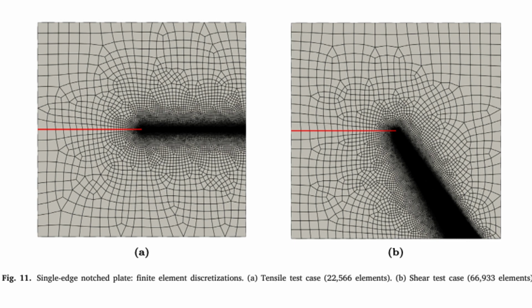This is where their novel line search comes in. Instead of monitoring the energy value, they decided to monitor the energy gradient, specifically the derivative of the energy functional with respect to the step size, lambda. Okay, explain that. They're looking at the slope instead of the height. That's a perfect way to put it.